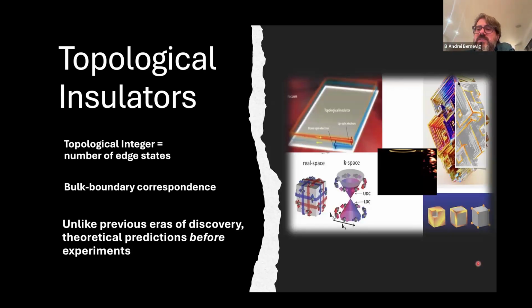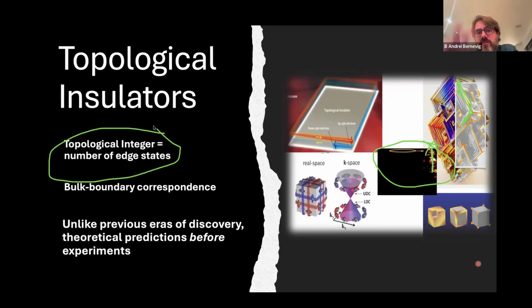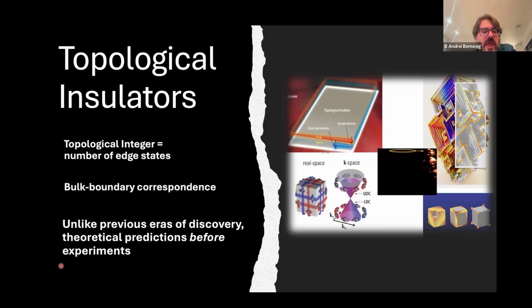On the surface, for example, this is bismuth, and this is an artist's rendition of bismuth, but you can see it's got these hinge states here. And this is a photonic crystal where you excite light, but in the bulk, you have a photonic gap, so you see no light, but on the edge, you see these edge states moving in, and this is because this is a photonic crystal with a topological number in the bulk, so it gives rise to the edge states. And basically, this topological integer is really the number of edge states or number of things that live on the boundary.